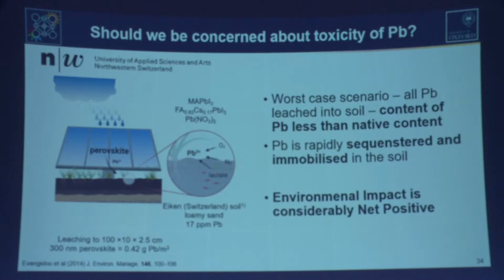So of course we take this seriously, and we've looked at the environmental fate of lead in perovskite solar cells. But it turns out when you do a full life cycle assessment, the environmental impact of lead is extremely small. As an example, we looked at the production of a perovskite on silicon tandem factory, and we looked at the ecotoxicity impact of lead in that whole process, and it amounted to 0.3% of the overall ecotoxicity of the manufacturing. In fact, the silicon wafer itself amounted to 40%. So the heat and energy that goes into producing the silicon actually creates far more of a toxic effect than the lead in the solar cells.